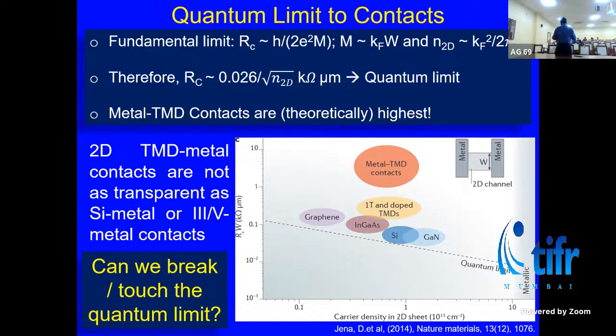We are just talking about two systems which are in the vicinity, so their Fermi levels will align, followed by charge transfer. If the charge on both sides is not aligned, there is a charge transfer from one side to the other, and a depletion will form in the region that is transferring charge. If that region's density of states or the strength of charge present is orders of magnitude different than the other, there is typically not much charge, right?